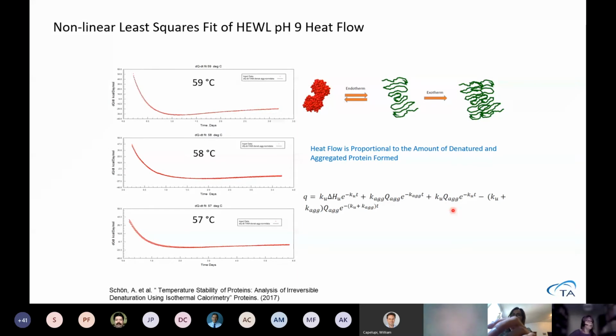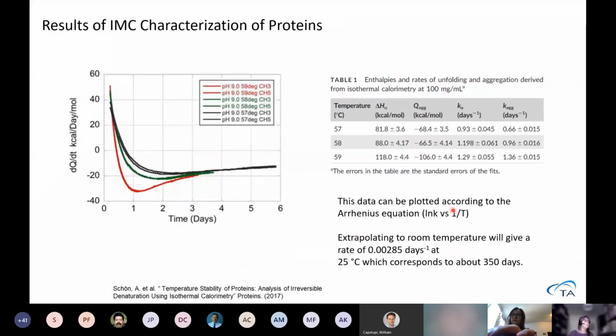And if we have fitted this data at a different temperature, we can calculate a reaction rate for unfolding and reaction rate for aggregation. If this now is plotted again in an Arrhenius relationship, where we take the reaction rate versus the inverse of the temperature, we can say that this will correspond to a reaction rate that it will be aggregated in 350 days. So this is a way of doing it.